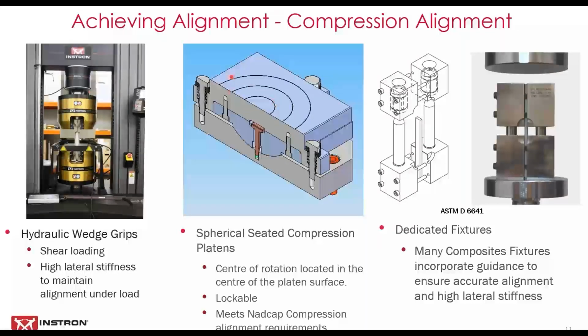Often the compression testing is being done between compression platens, and in that case it's important to have the ability to align the compression platen, in this case usually performed by having a compression platen with a spherical seat. So we have a pair of compression platens, one with a spherical seat, one fixed. They can be driven together and then locked up once they are perfectly parallel, and that kind of thing will meet the requirements that NADCAP state for compression accuracy of platens.